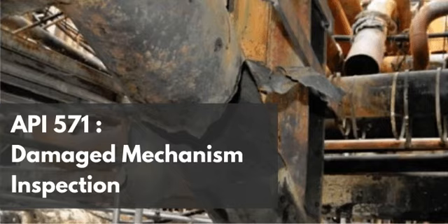It does. It often transforms the relatively soft ferrite and pearlite into harder, much more brittle microstructures like untempered martensite or bainite. Oh, wow. So right next to your weld, you have accidentally created a localized band of high-strength, low-ductility steel. Exactly. And on top of changing the microstructure, the welding process also leaves behind a massive physical force. The residual stress.